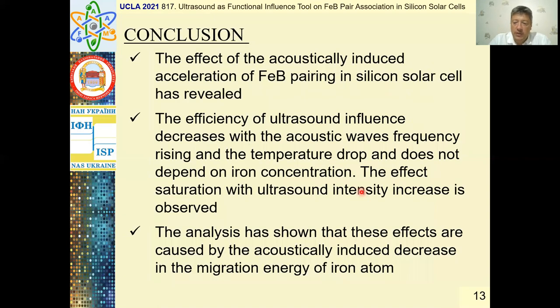Therefore, the conclusions are following. The effect of acoustically induced acceleration of Iron-Boron Pairing in silicon solar cell has been revealed. The efficiency of ultrasound influence decreases with the acoustic wave frequency rising and the temperature drop, and does not depend on Iron concentration.